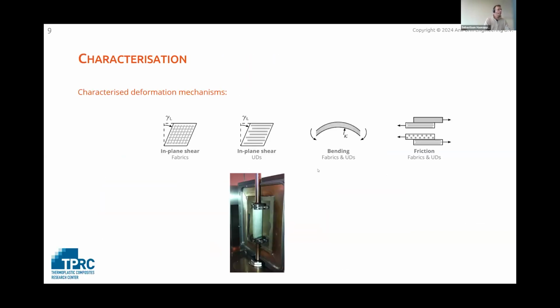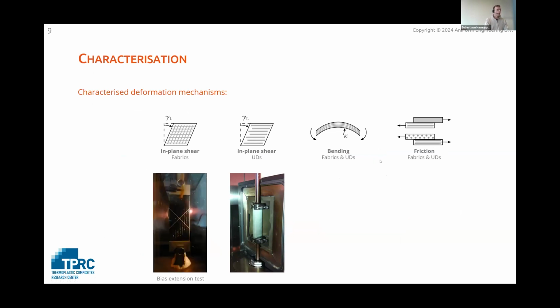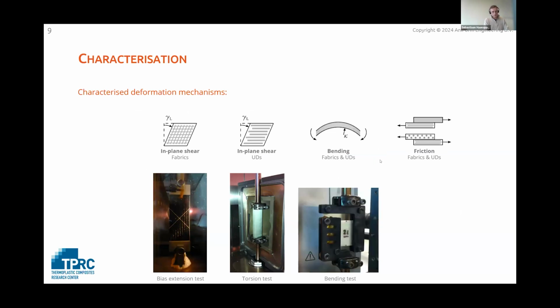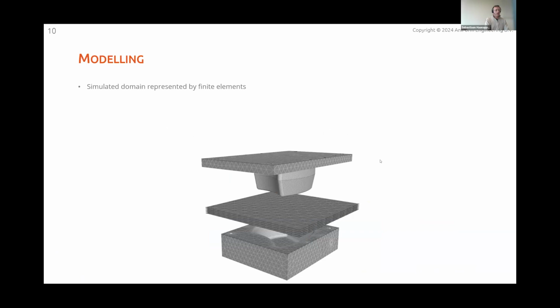Okay. So the characterized deformation mechanisms are in-plane shear for fabrics and unidirectionals. We characterize bending for fabrics and UDs, and we characterize friction for fabrics and UDs. And we use the bias extension test for characterizing shear of fabrics. We use the torsion bar test for characterizing shear of unidirectionals. We characterize the bending behavior using a bending test in a rheometer, and we characterize the slip using a friction tester. And that is a program today offered by the TPRC. So we have that characterization generally available in those results.